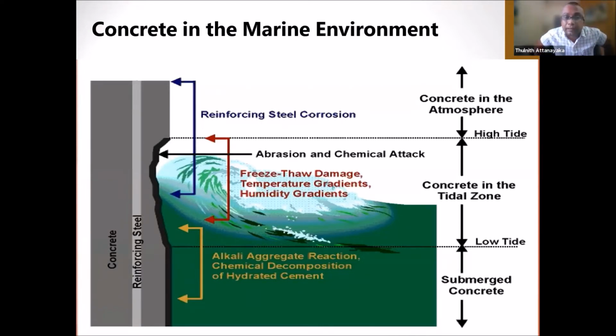Corrosion in the marine environment, like you can see this concrete in the tidal zone. Let's say we have reinforced concrete, a pipe, and you can see the area between the tidal zone, low tide and high tide. That is the most vulnerable and most critical part we have to protect. Abrasion and chemical attack are also there, because with the waves and all, it will abrade the surface concrete, and there is also very much oxygen-rich water. So all the elements which are very hazardous to the structure will be there between the high tide and low tide, that is the concrete tidal zone.